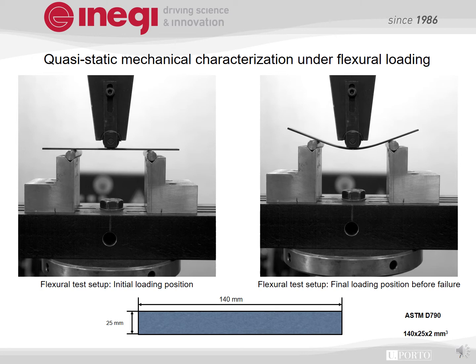This standard utilizes 3-point bending system as a simply supported beam shown in figure. Specimens rest on two supports and was loaded by means of a loading nose midway between the supports. A support span to depth ratio 40:1 was used for setting up a 3-point bending system. The figure on the left hand side shows the flexural test setup in the initial loading position, and on the right hand side shows the final loading position before failure.